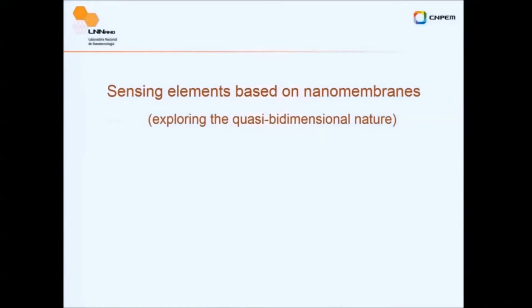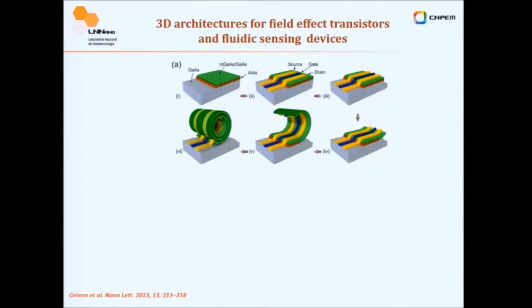All right, moving a little bit. How can you do sensing elements with nanomembranes? So the first approach, both approaches start simultaneously, but I present this one, that is basically using III-V. Here the sacrificial layer is not germanium dioxide, but a sacrificial layer of aluminum arsenide, and the membrane is based on indium gallium arsenide and gallium arsenide. So it's strained, but not so much that you form quantum dots, but the layer is under stress. And then when you remove with HF, the system curves.